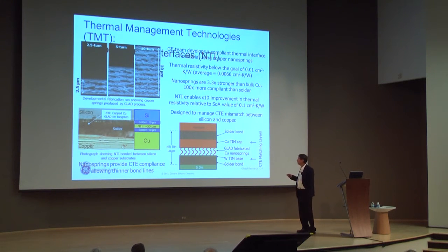So what we developed here was what we call copper nanosprings. It's what it looks like, it's copper springs, basically. Actually, it's copper and tungsten. They connect the silicon die to the heat sink, and it turns out that they are three times stronger than bulk copper in this position, and that you can get a 10 times improvement in thermal resistivity relative to the standard state-of-the-art values by using something like this. So that was an improvement that we've worked on recently.